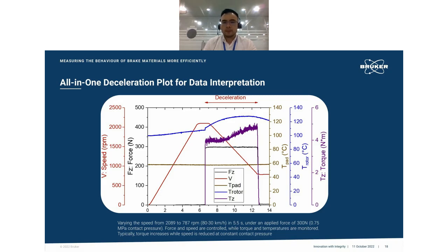So force and speed are controlled, while torque and temperatures are monitored. At the same time we monitor the temperature of the pad, the temperature of the rotor, and the torque, which is then used to determine the brake effectiveness throughout the deceleration test. The region that we are interested in is shown by the double headed arrow on the top, which is where the deceleration is, and that is also where the torque and coefficient of friction are calculated.